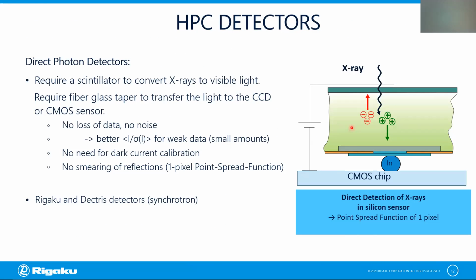I don't have the time to get into too much detail here, but just know that with HPC detectors, or direct photon counting detectors, X-ray photons are transformed immediately into an electrical signal via the generation of electron-hole pairs within the matrix in which the photons penetrate when they hit the detector. Then you apply a certain voltage difference to that matrix. So one type of charge moves one way while the other type moves the other way. And then you count one or the other. Here we count the plus charges on the electronics, with the electronics down here. I want to point out that this whole process is unique to each pixel. That means that each pixel has its own readout line,